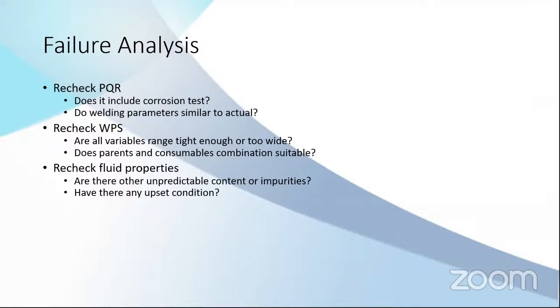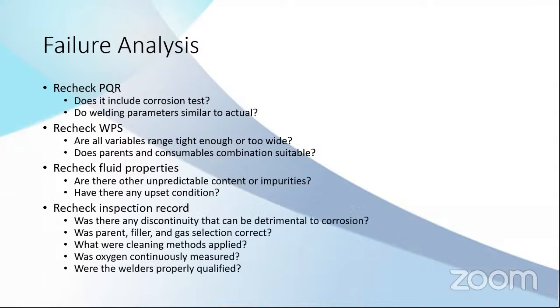Recheck the fluid properties. This may not be related to the welding, but it is related to the surface itself. Probably there was an upset condition. For example, the chloride content suddenly getting high, or the H2S content suddenly getting high, then it may cause increased corrosion on the weld area.